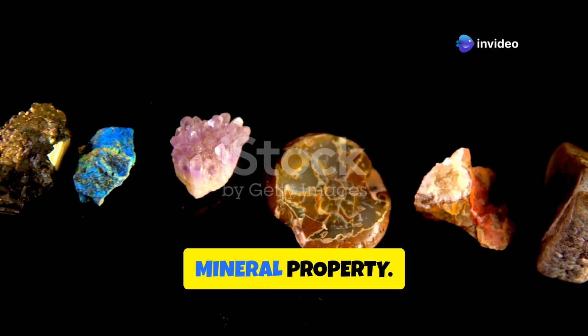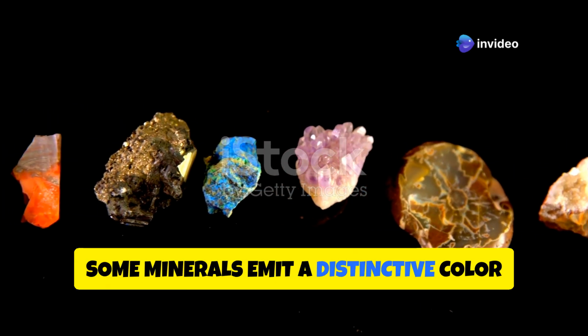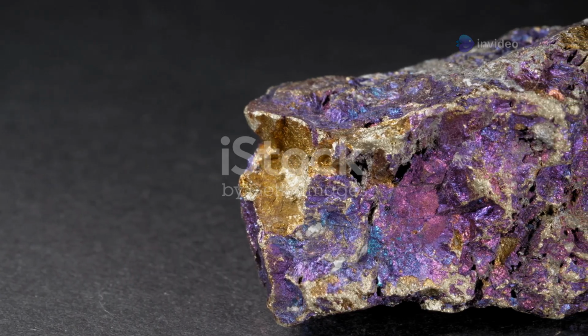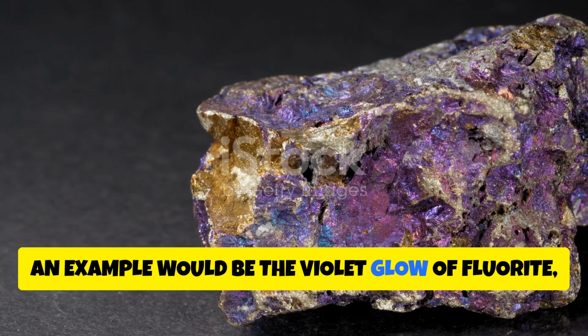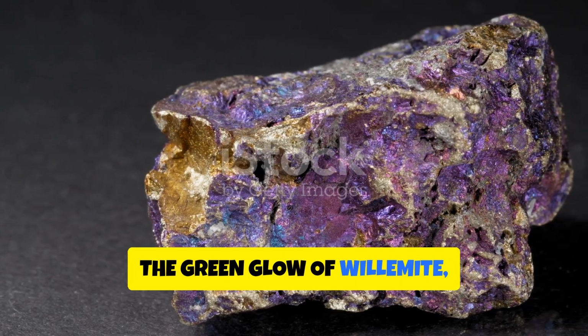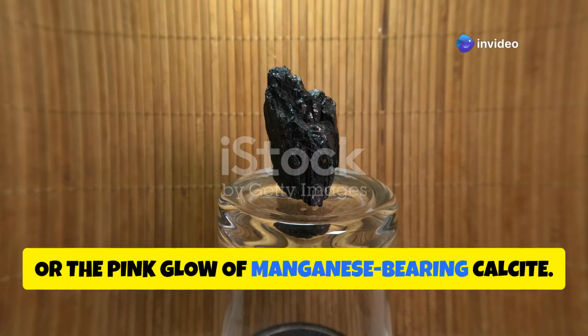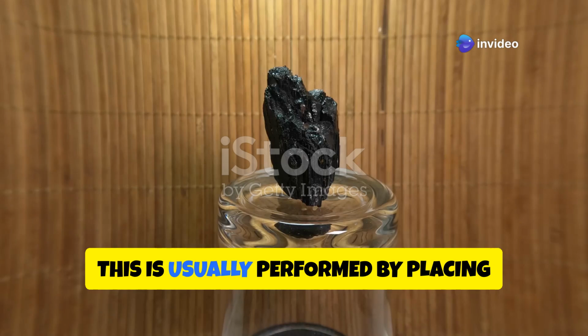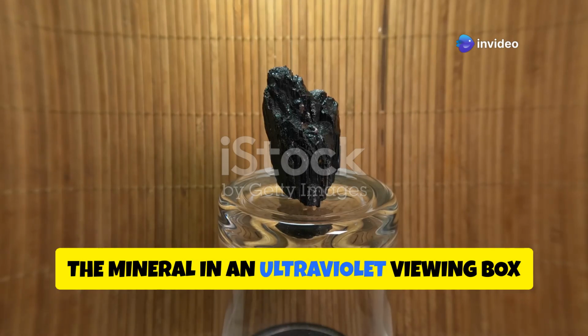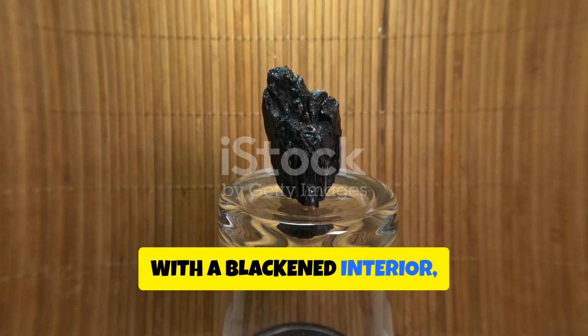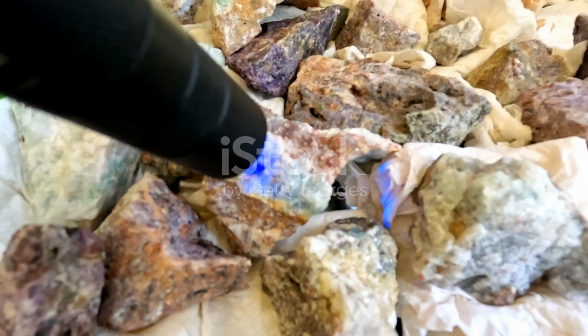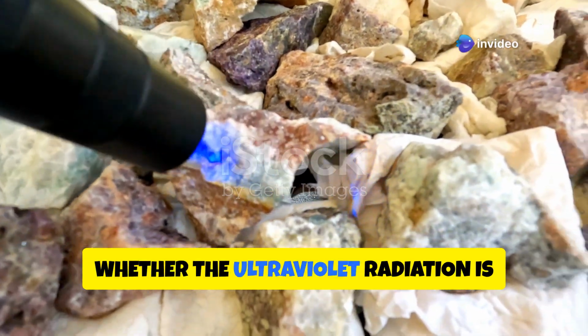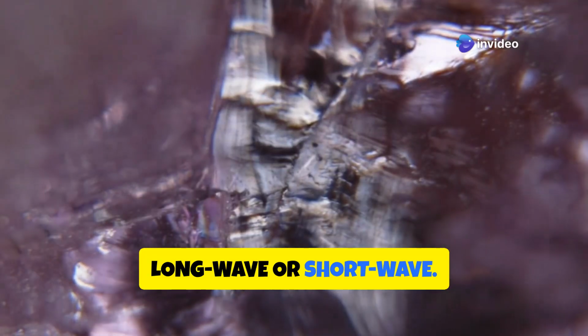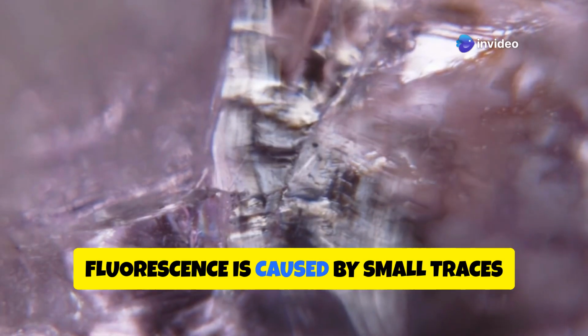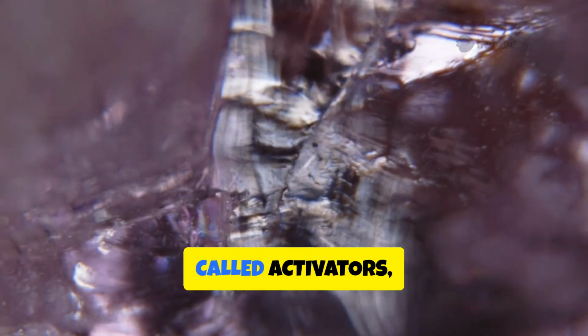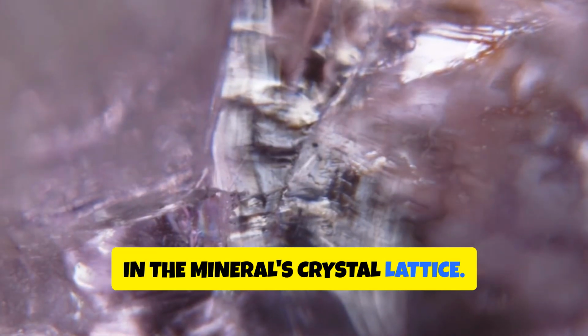Fluorescence is another identifying mineral property. Some minerals emit a distinctive color under ultraviolet light. An example would be the violet glow of fluorite, the green glow of willemite, or the pink glow of manganese-bearing calcite. This is usually performed by placing the mineral in an ultraviolet viewing box with a blackened interior in a darkened room. The color can also vary according to whether the ultraviolet radiation is long-wave or short-wave. Fluorescence is caused by small traces of impurity elements, called activators, in the mineral's crystal lattice.